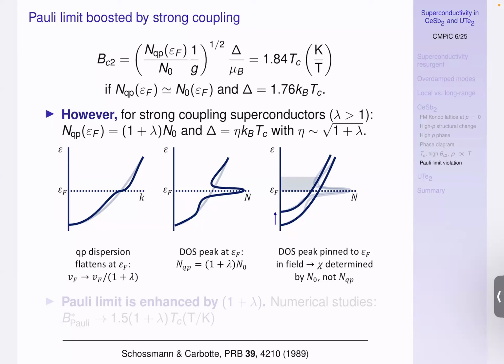And there's another issue: in the Pauli limit calculation, the relation between the gap and TC plays a role, and that ratio is 1.76 in normal BCS theory, but it can be much higher in strong coupling. So when you take those two aspects together and you do a strong coupling calculation for a phonon-mediated superconductor, you find that the Pauli limit is actually much higher than one would think. It's not, let's say, 1.5 times TC. It's 1.5 times 1 plus lambda times TC. This was found in the 1980s by Schossmann and Carbotte. The number of papers on that topic look pretty convincing. Of course, in phonon-mediated superconductors, lambda is of order 1, so this is not a huge factor.